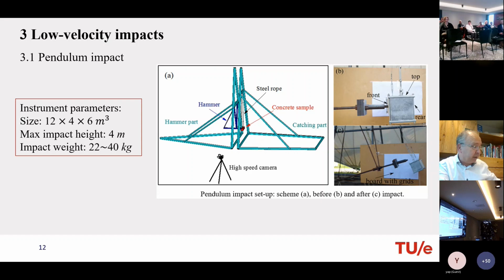Well, here is a little bit of information about the test methods that we did, the dynamic test methods. We also did, of course, static tests, but they are not so spectacular. We know them all. This is a so-called pendulum impact test. It's 2 frames which are not connected with each other. We have a concrete sample hanging here, a beam, and with a hammer we let it collide and we look how far it goes, and after how many punches the concrete will be damaged, broken.